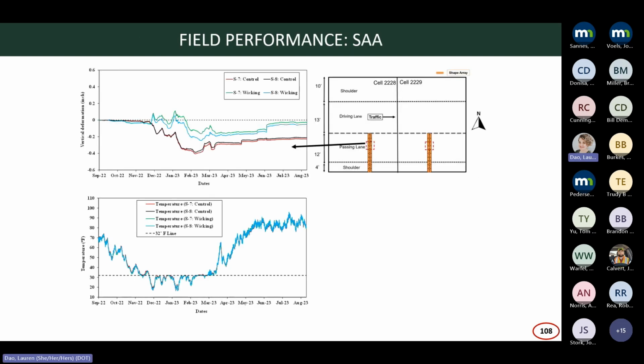And these are the shape array results, the shape array sensor, which was measuring the deflection in the pavement. So during the springtime, I am plotting the deformations for two segments inside the pavement. And as you can see, the red and black lines, those are of the control section. We are seeing more settlement during the thawing. On the other hand, for the wicking section, we are seeing less deformation here in the blue line and the green line.